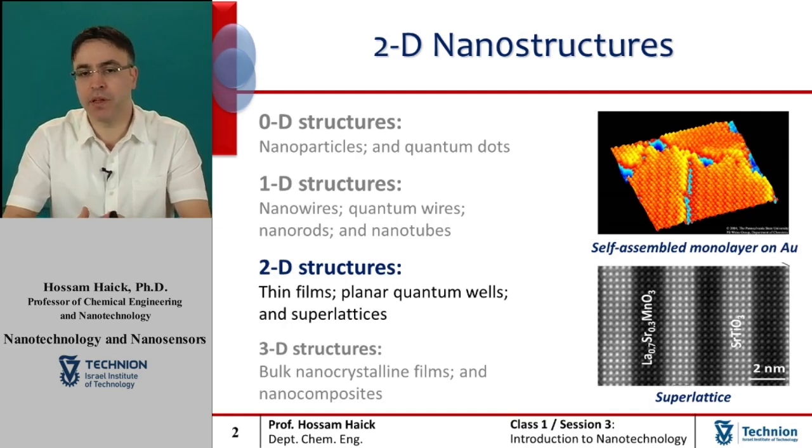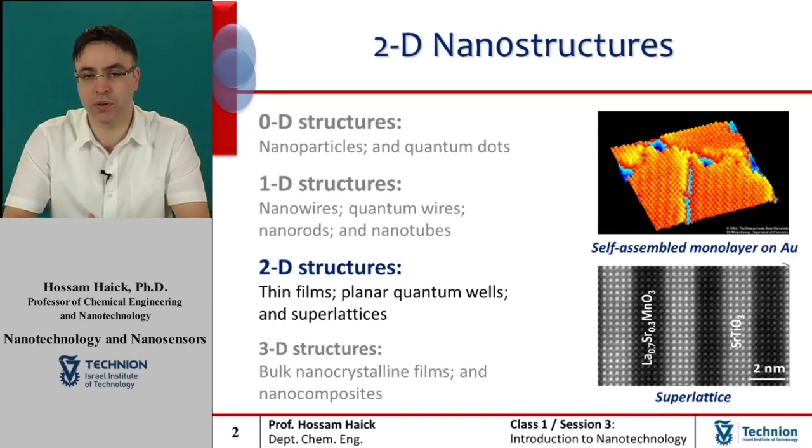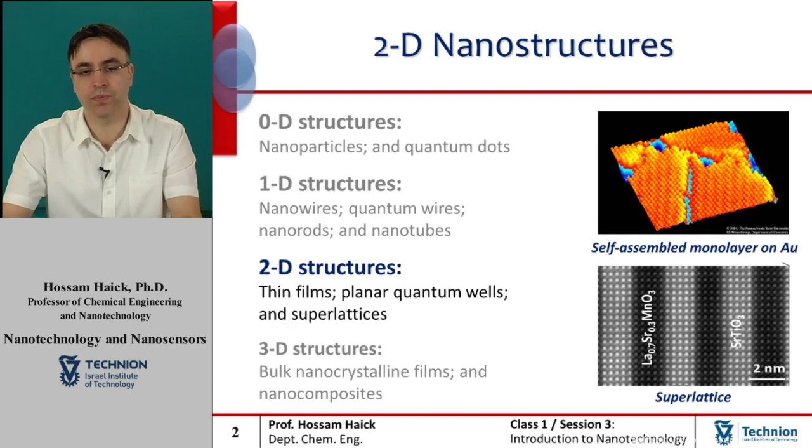As a representative example of thin film, please have a look at the scanning tunneling microscope image of a self-assembled monolayer of N-decanethiolate on gold surface. As seen in the image, the individual molecules are closely packed into a hexagonal array. Also, one can see clearly the features of the assembly and the surface, namely, domain boundaries, which are highlighted with light blue strips on the figure, and gold vacancy islands, which can be seen as circular blue spots.